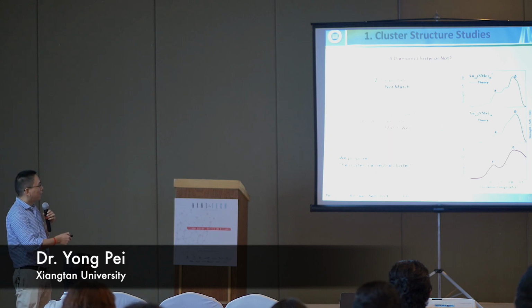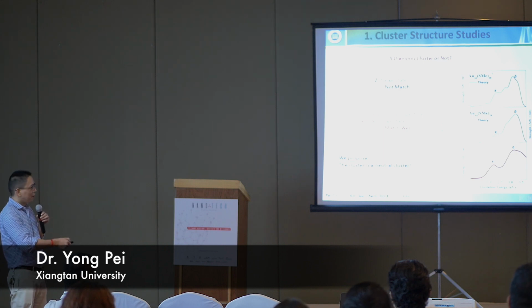So we worked on this issue for a long time, and finally, we think this cluster may be in a neutral charge state and not an ionic state. So we recalculated the spectrum using TDDFT based on the neutral charge state. Okay, things changed. The spectrum fit very well with the experimental one. So we propose this cluster is a neutral cluster, and this model might be a very good candidate structure model.